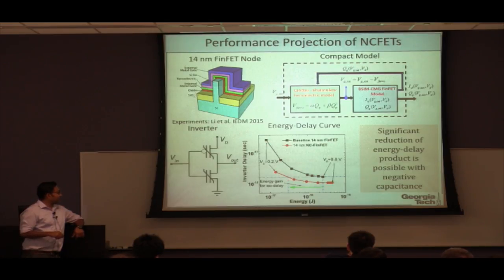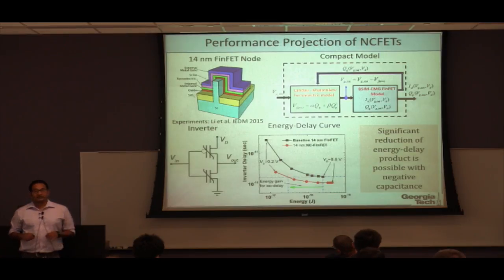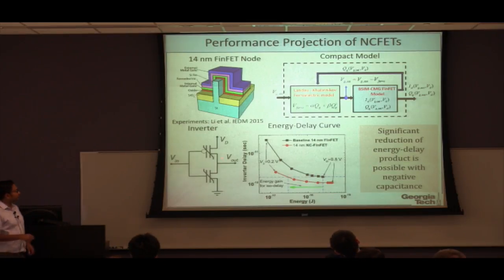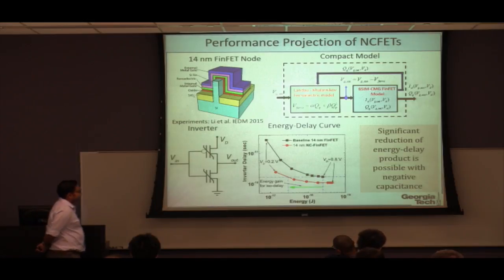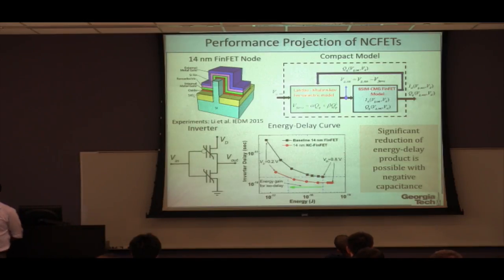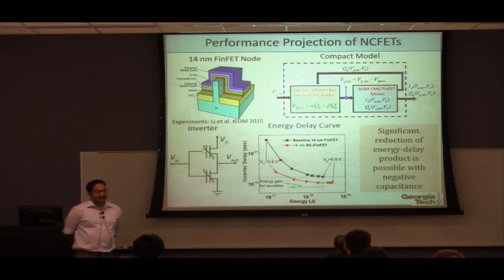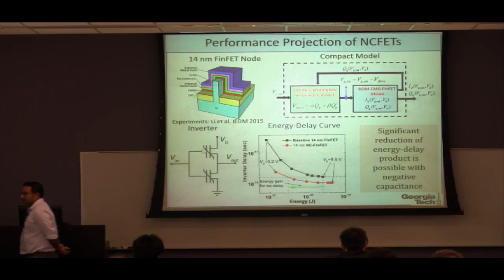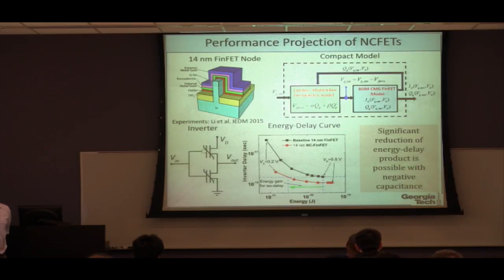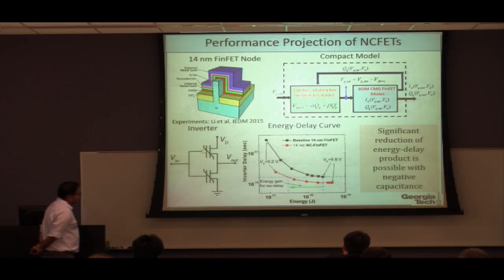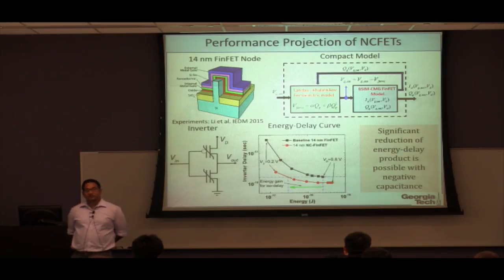But what is important to note here is that when you use a negative capacitance transistor, for the same delay, you can actually operate the device at least one order of magnitude less amount of energy. Again, this essentially means that if you want to operate an NC FET at the same frequency as that of a regular transistor, for the same frequency, you need much less energy.